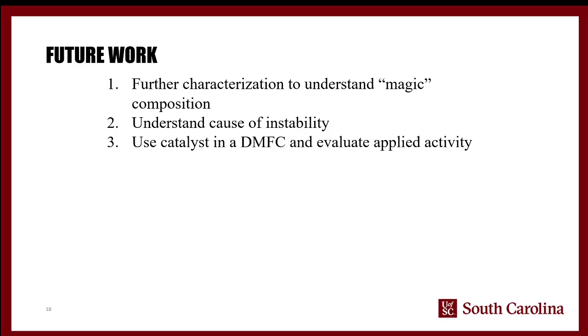And so going forward, one of the big things that we need to do is some more characterization to try and understand this sort of magic composition, whether it's the platinum 3 nickel or the platinum 2 cobalt. We need to figure out why those work the best. We also need to work to understand the cause of the instability. Like I said, you can have the best catalyst in the world, but if it's not stable, then it's not really going to do you much good.